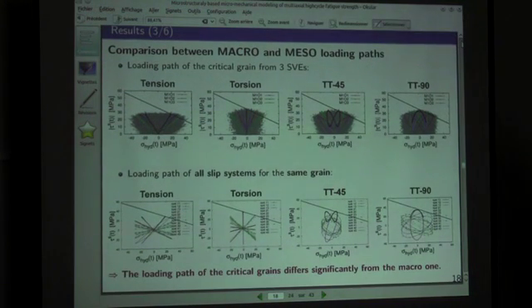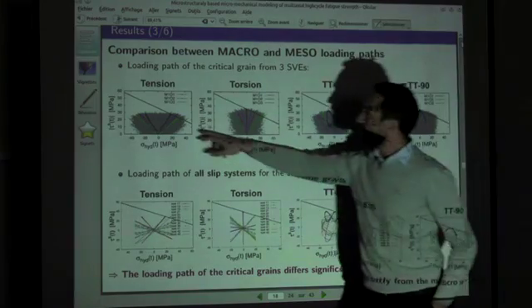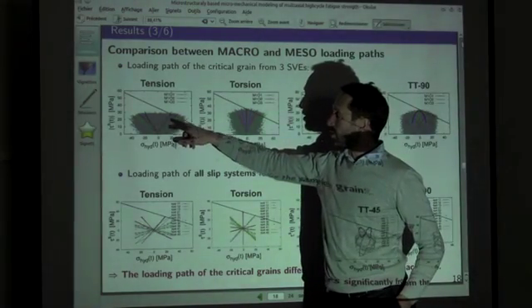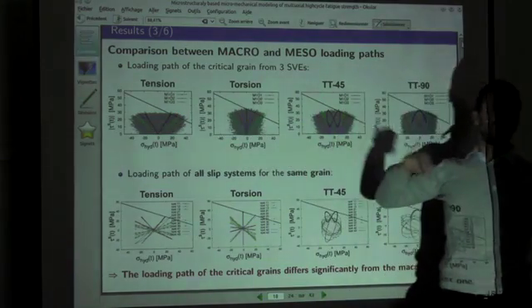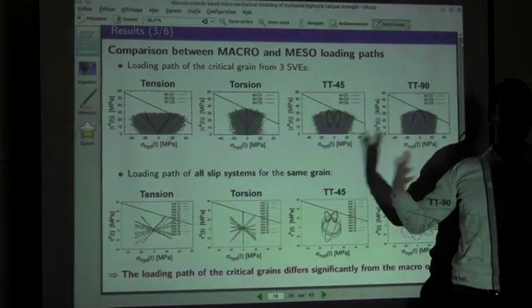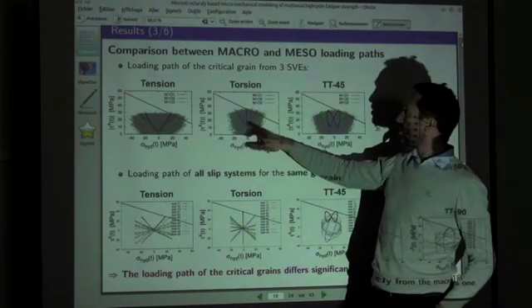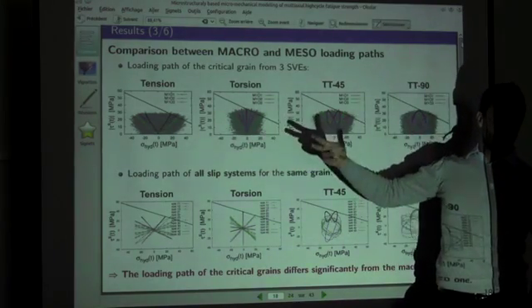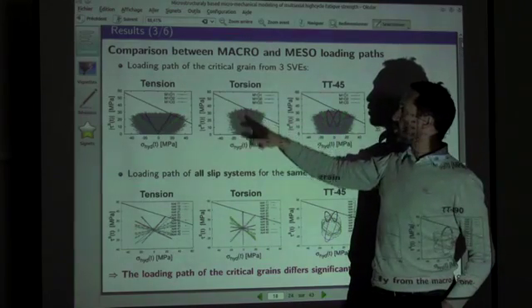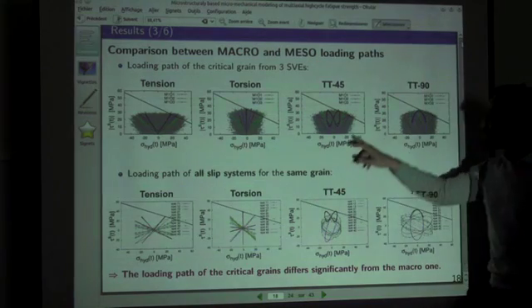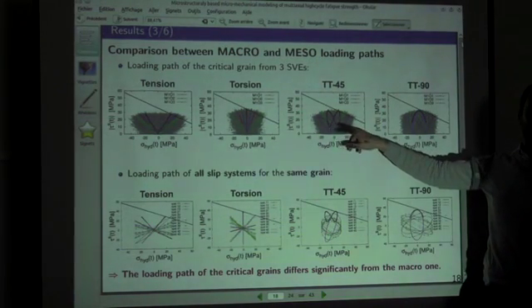Another thing that we are interested in, I will skip this one, go directly to this one. We have been talking a lot in this workshop about loading path and trying to evaluate the loading path and trying to relate it to the fatigue life. But when you look here at different microstructures, here are the different paths that are related to the grains which are critical. So this is a critical grain for the aggregate. And you compare the loading path of those grains with respect to the loading path that you compute macroscopically. And what you can see is that the macroscopic one is very far away from the mesoscopic one.